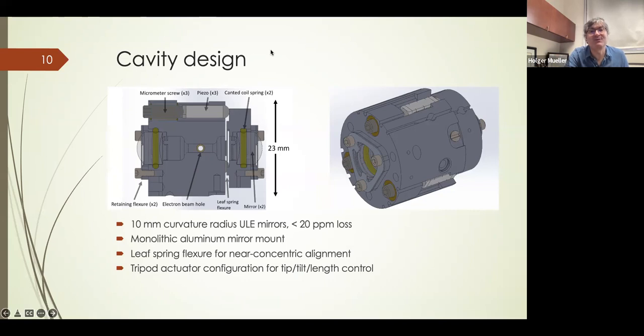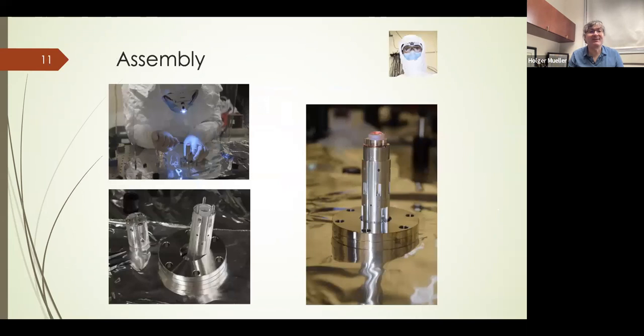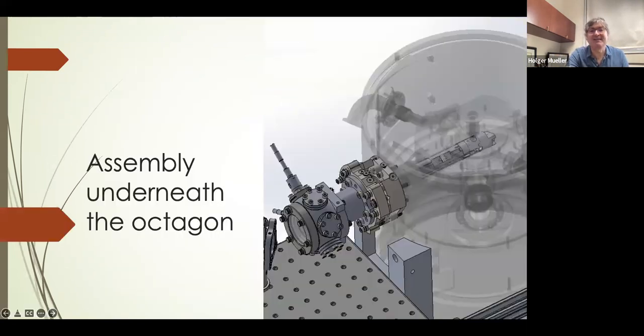The other feature I want you to note is that this whole thing is engineered to fit into a 1-inch port in the microscope column, and the electron beam has to pass through a 2 millimeter hole here. That will become relevant later. At these high intensities, you can imagine that a single speck of dust burns into the mirrors very fast. So this whole thing has to be assembled under clean room conditions. And then it's being integrated underneath the octagon, underneath the objective lens. And the cavity sits at the end of this holder, and the laser beam enters from here.